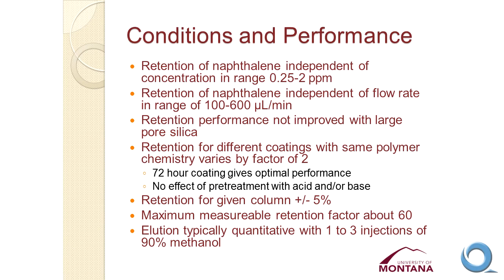All right, some things that we investigated early on. We wanted to make sure that we really were working in that linear region where retention is not a function of concentration, and we found that for naphthalene, we could vary the concentration between 0.25 and 2 parts per million and not see any change in the retention. And so we typically use 0.5 or 1 part per million solutions for all of our studies from that point on.